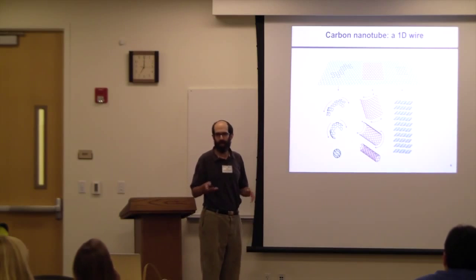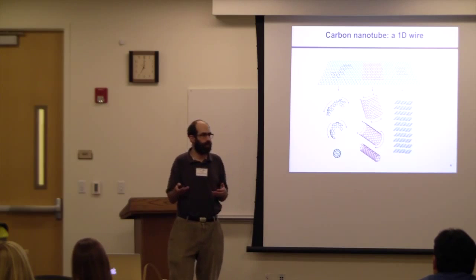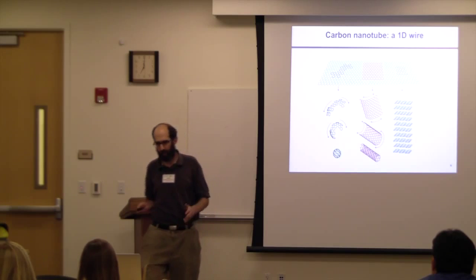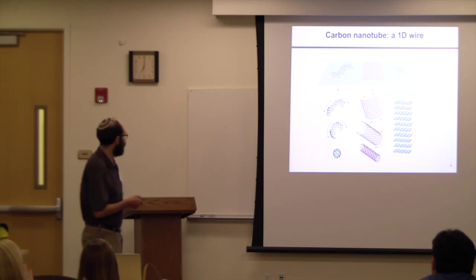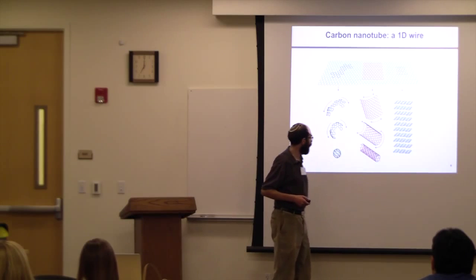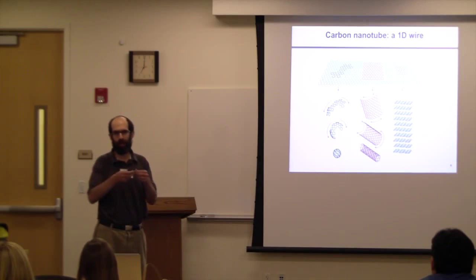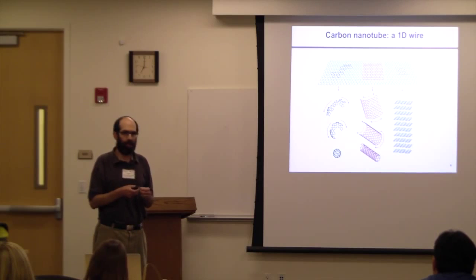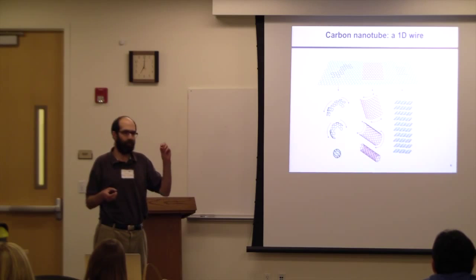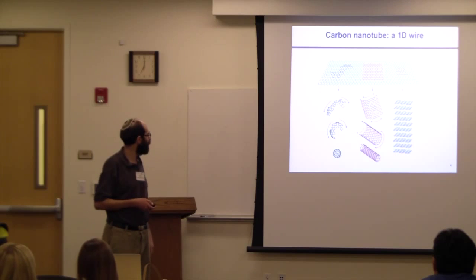Now, this is not actually how people make these. Rather, you can make carbon nanotubes typically by having a hot furnace with carbon, and if you tune it right, then you can grow tubes. So I can tell people more about it if they're interested. But these objects tend to have a diameter of one or a few nanometers, so not too many atoms across. And so you can see that it's a very one-dimensional system. You can make these that are tens or hundreds of microns long, or even a millimeter long, and yet they're only a nanometer in diameter. That's about as big an aspect ratio as we tend to have in scientific fields.